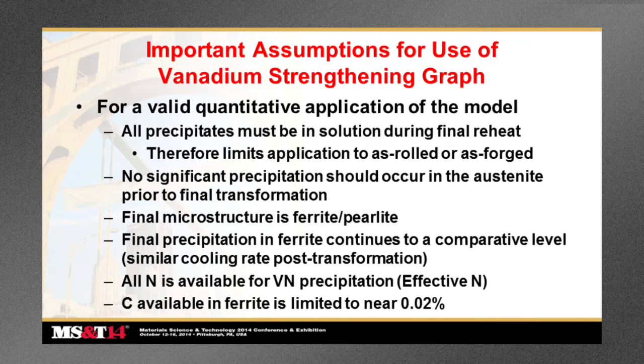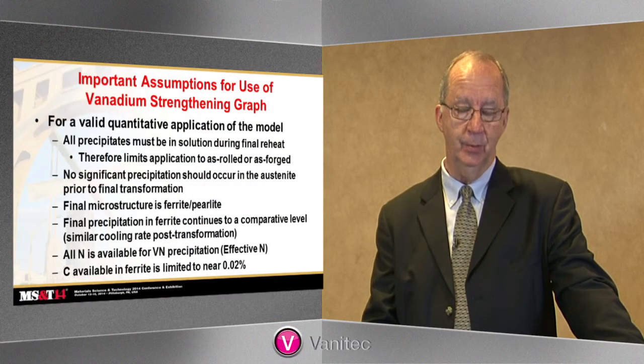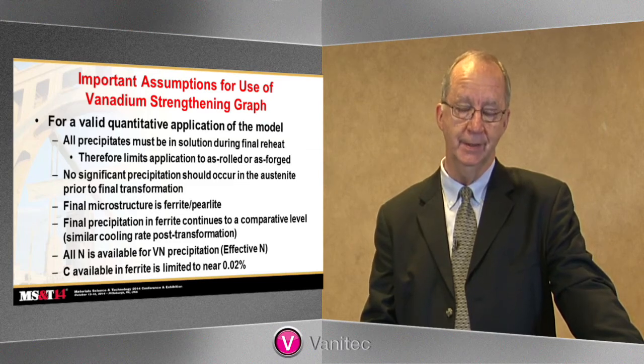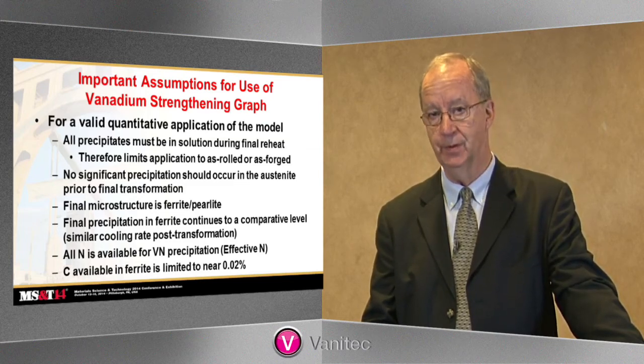You have to be looking at a situation where all precipitates must be in solution in the final reheat. That means the reheat temperature should be high enough to get all of the microalloys in solution, certainly all the vanadium in solution that you're looking for the precipitation strengthening. However, things like titanium, you may never get back in solution once the steel is solidified. But it does mean that there probably has to be a reheat temperature much higher than normal austenitizing temperatures for heat treatment, such as normalizing.